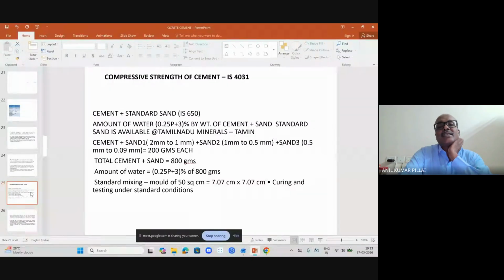Unlike concrete testing, which, as all of us know, is done on a 15 centimeter by 15 centimeter cube, the cement mortar strength is actually done on a 7 by 7 centimeter cube mold, and it is basically done under standard conditions. So the standard sand which is available from Tamil Nadu is being used. So the basic idea of having a standard test is that it becomes easier for us to evaluate the various types of cement that are available in the market. So when you have a standard test like this, you can compare the types of cement that are there.